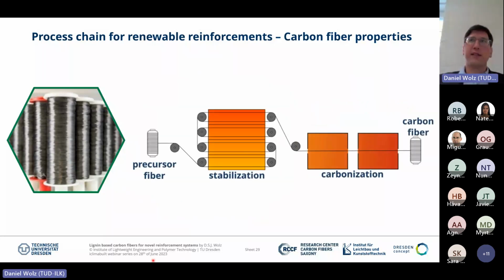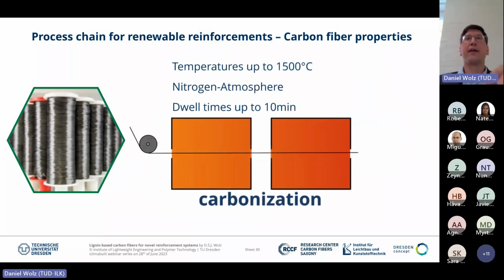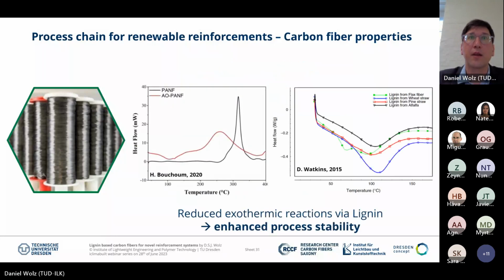If we look at carbonization itself, there we have two ovens, one for low temperature, one for high temperature. At maximum, it is going from 400 degrees to 1500 degrees Celsius. We have a nitrogen atmosphere to push out every hydrogen atom, and the dwell times range between 1 minute to 10 minutes. But what is actually the difference between polyacrylonitrile and lignin?